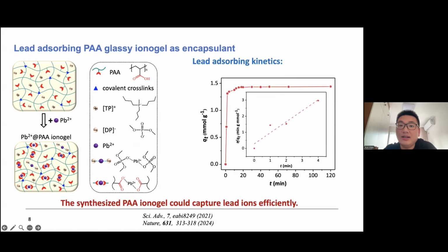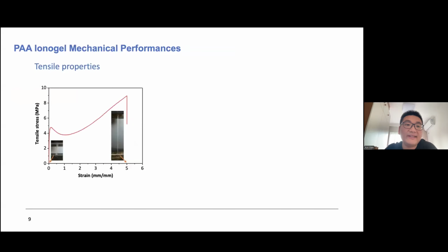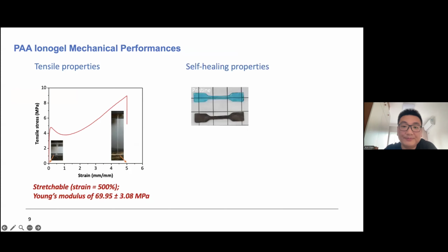So this is the typical lead absorbing kinetics that we have measured. This shows that our newly synthesized PAA ionogel can capture the lead ions efficiently. So we want to use this ionogel as an encapsulant for the perovskite solar module. We tested the mechanical performance to know whether this PAA ionogel can be a physical blocking encapsulant. As it's a gel, we can make it stretchable. We have a strain of around 500%, and the modulus that we can tune to be very suitable for the encapsulant. And more importantly, we have the self-healing property for the encapsulant.